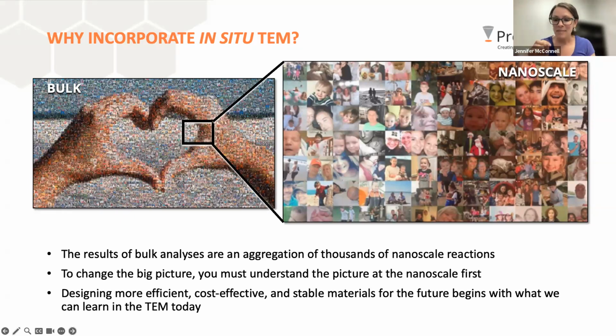You're using a TEM to understand how the atoms and the nanoparticles and molecules interact with each other under certain conditions. And so if you want to change the big picture that you see when you're doing your bulk scale tests, which are just aggregates of bazillions of nanoscale reactions at once, right? If you want to change the big picture, you're going to have to understand those interactions at the atomic and the nanoscale to be able to do so. And so incorporating in situ TEM gives you information you can't get anywhere else.